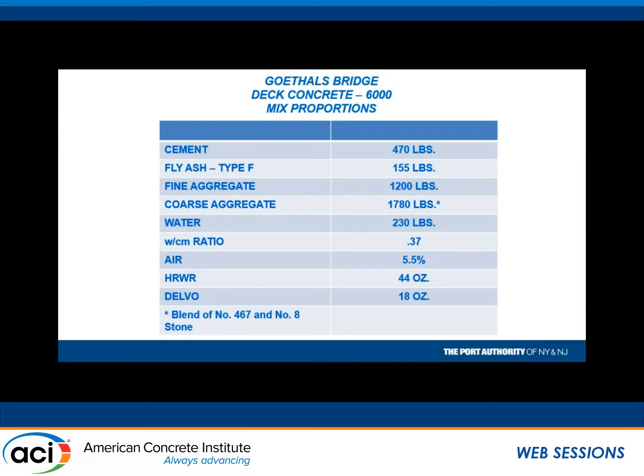And it's interesting, I was against putting in that hydration control admixture because of fear that someone will overdo it and the concrete will sit on a deck for 24, 48 hours, and then you're going to have a lot of cracking. But when working with Kiewit, they showed us, we had mock-ups, and we just couldn't finish it after 60 minutes. 60 minutes after the water met the cement. And the concrete was kept below 75 degrees. If the concrete was higher than that, we would substitute some ice for the water. We kept the temperature of the concrete below 75 degrees. And Kiewit was very good at doing that. And yet we couldn't get the right finishability to that concrete after 60 minutes.